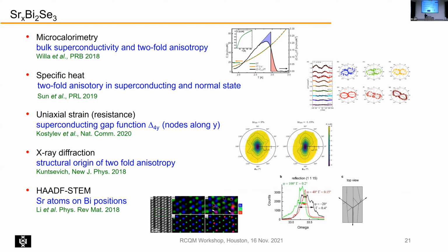Question: for the calorimetry, is that transition within the superconducting state? Yeah, the transition is 3 Kelvin. Is it at the same point where you go superconducting? Yes. That's just the superconducting, a BCS superconducting transition. But they don't know the gamma value for this exactly. But from this, they claim it's bulk superconductivity. So the anisotropy develops at the same point with the superconductivity.